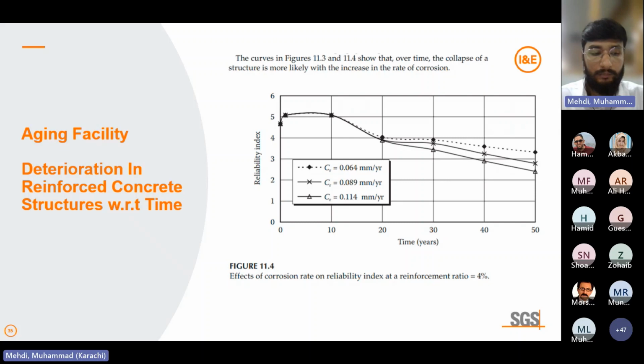So in these cases we understand that in case of higher steel ratios and lower corrosion rates, this period may increase to about 15 to 20 years. Moreover, this study expects that in the case of columns with eccentricity, the moments on the column will increase, so the design should increase the percentage of steel. In such cases, it is expected that the deterioration of a structure towards criticality will occur after a couple of years in the case of a lower reinforcement steel ratio and very high corrosion rate. On the other hand, as in this graph, in the case of a higher reinforcement ratio and lower corrosion rate, maintenance will be due somewhere around 5 to 10 years.